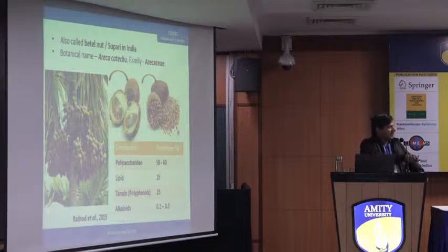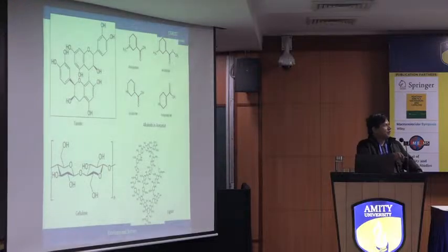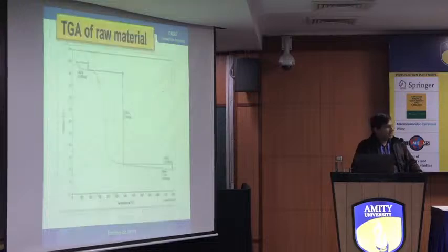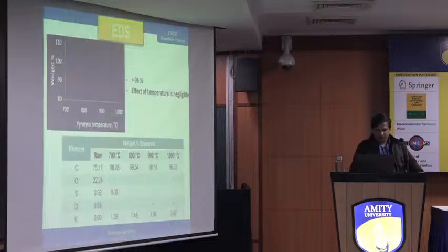We took it because the tannin level in this one is extremely high. You can see here 15% tannin is present in these kinds of structures, and again a lot of OH groups. You can see the alkaloids, tannin, cellulose, lignin. The TGA is very attractive compared to any bio-waste material reported in the world so far. You can see that at 400 itself, you can synthesize the nanoparticle. It's a very stable material. After 400 until 1000, it is almost constant. So then we synthesized nanoparticle from 700 to 1000.